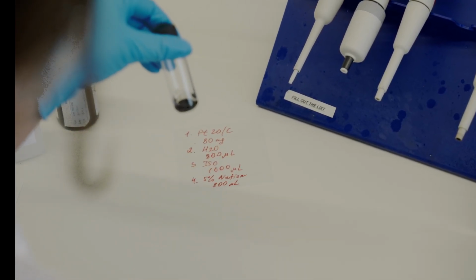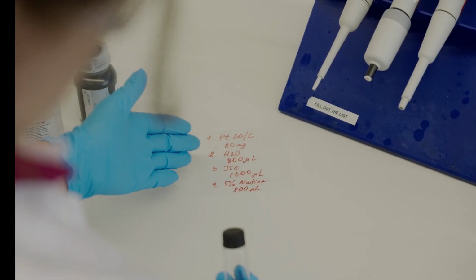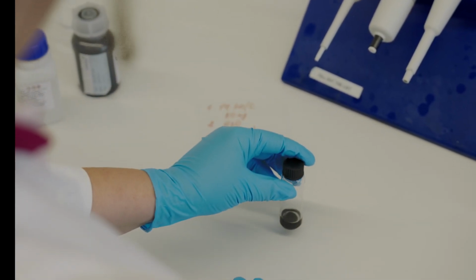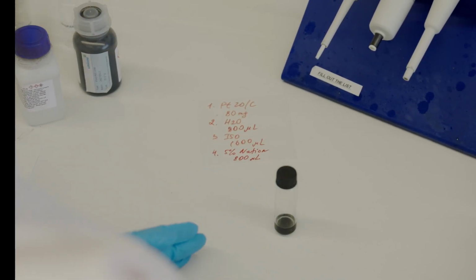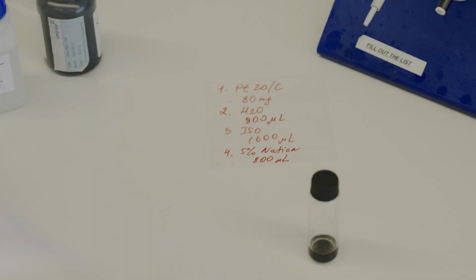All 4 components are in a glass bottle. The catalyst layer is to be formed by them. To obtain a homogeneous ink, the 4 components are dispersed using an ultrasonic device for 1 hour with ice added for cooling.